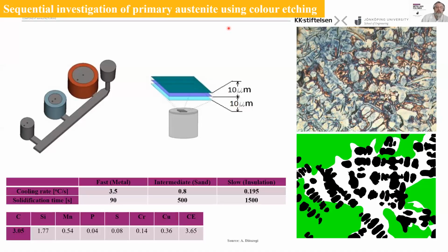So color etching was very, very useful to understand how the austenite network forms, or how the austenite network looks in a cast iron. For this reason, we performed a sequential investigation by using a part of a sample, preparing, etching and taking a picture, and then reiterating the same process by polishing again, taking away approximately a couple of micrometers of the surface, re-polishing, re-etching, and a new picture. In that way we could go through the structure of, in this case, laminar cast iron, hypoeutectic laminar cast iron.